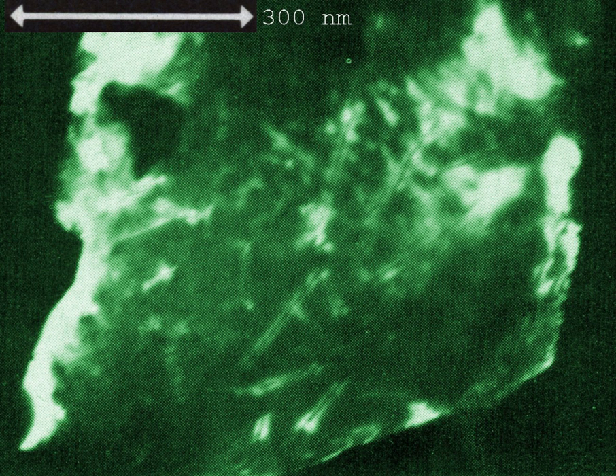Metal replicas can be obtained either by electroless deposition or by electrodeposition. For replication of through pores, a cathode film is deposited on one side of the membrane, and the membrane is immersed in a metal salt solution. The cathode film is negatively charged with respect to the anode, which is placed on the opposite side of the membrane. The positive metal ions are pulled toward the cathode, where they catch electrons and precipitate as a compact metal